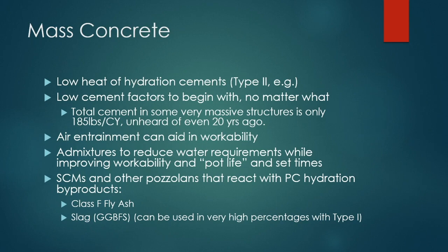They do talk about in the document that air entrainment can really aid in workability, even in situations where freezing and thawing isn't a big concern. So if you are working with mass concrete and you have no other way to improve the workability of your mix, you can consider adding an air entrainment admixture, even if you're not going to be subjecting the concrete to freezing and thawing. There are plenty of admixtures that they cite to reduce the water requirements while also improving workability, and also something called pot life, which is the ability of the concrete to stay fluid inside the mixer, and also delaying set times so that all of the concrete sets up together.